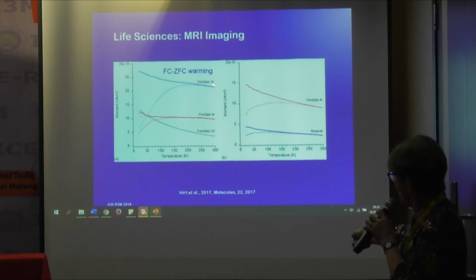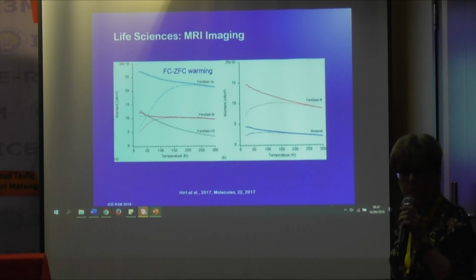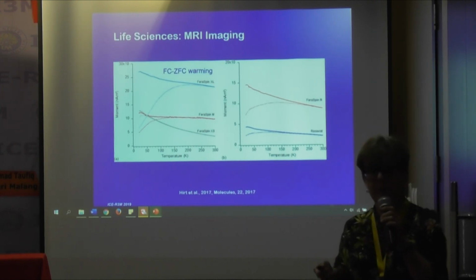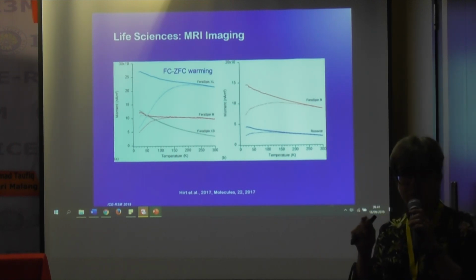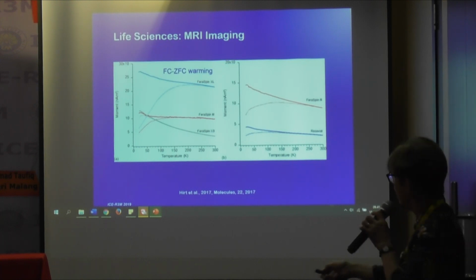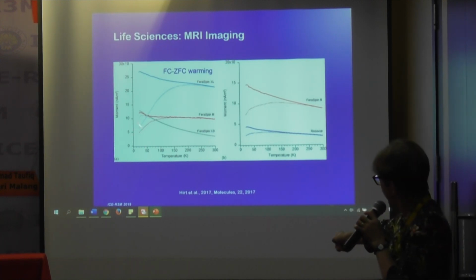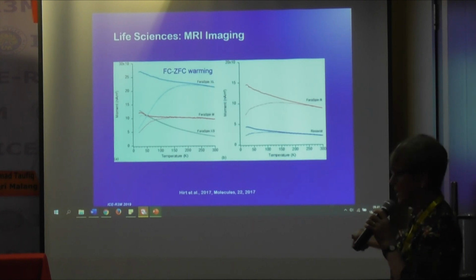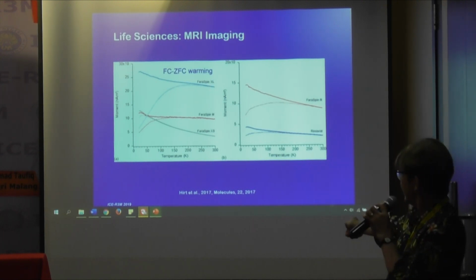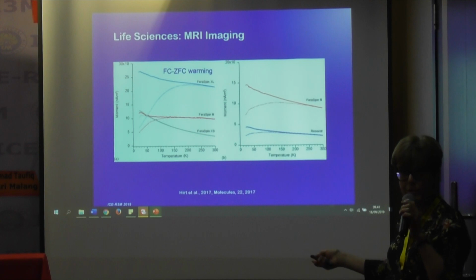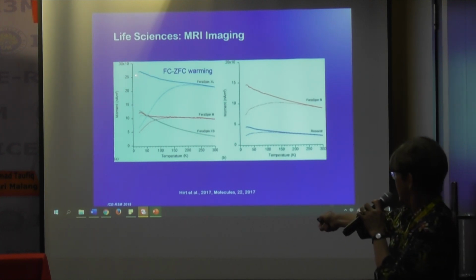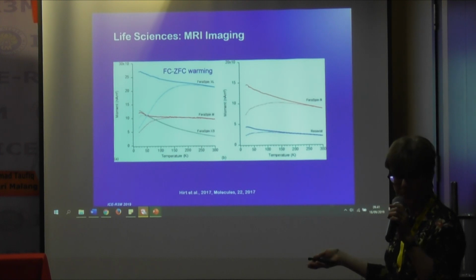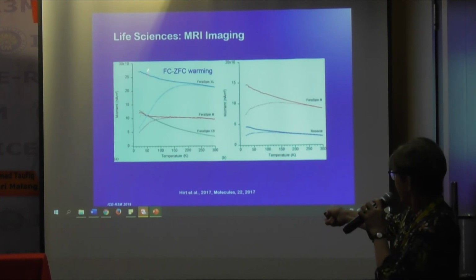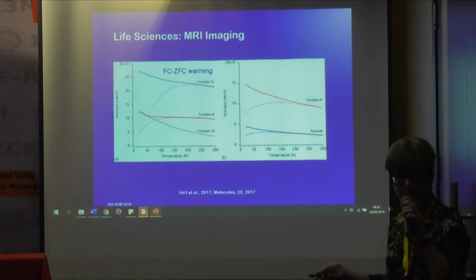You take a sample, you cool it down in zero field to about 15 Kelvin, then you apply a very weak field, and you measure essentially susceptibility as a function of temperature, starting at 15 Kelvin up to room temperature. Then you cool it down again in a strong field, 1 to 2 Tesla, or 5 Tesla, and then you warm it back up in a very weak field again, 50 millitesla, or 5 millitesla, 10 millitesla, and you measure the susceptibility.